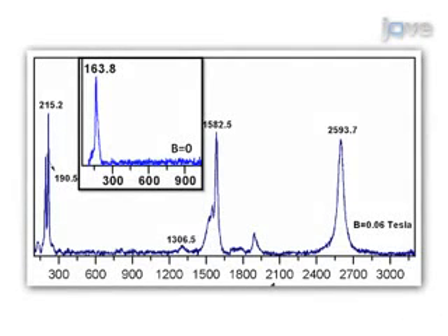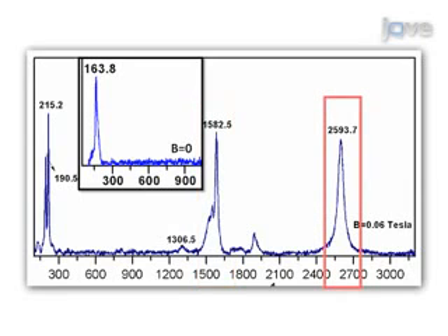Here is a Raman spectrum of samples in a range of 100 to 3100 per centimeter obtained with a magnetic field. The inset is for samples without a magnetic field around radial breathing mode frequencies. The intensity of the 2D peak over the intensity of the G peak is utilized to estimate the thickness of graphene layers. This spectrum produces an intensity value of around 1, which represents that the number of graphene layers is around 2.